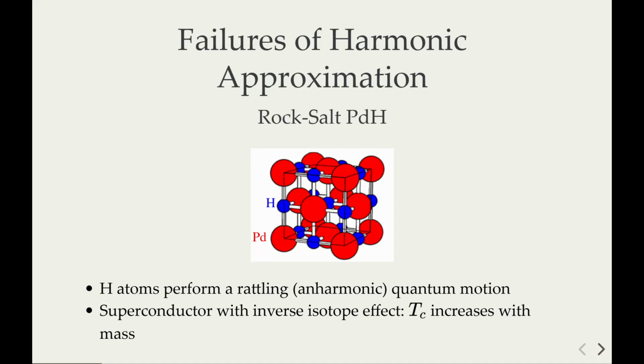I'm going to show you one very easy example, which is the rock salt palladium hydride. This system is stable at ambient pressure, and it is a superconductor, very well studied because of an interesting property: its superconductive critical temperature shows an inverse isotope effect. The standard BCS theory predicts that if you increase the mass of your system, your frequency decreases, and then the superconductive critical temperature decreases as well.